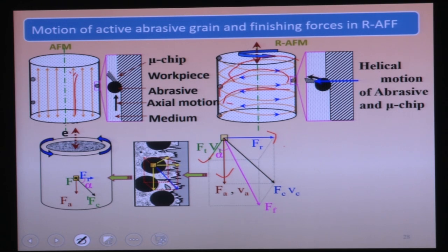Okay, so as it is flowing through a spiral path, it will generate a cross-hatch pattern on the workpiece surface. So these cross-hatch patterns are generated on the workpiece surface. This is actually helpful to retain the oil during the actual polishing of the cylinders of the engine, the engine cylinder, and also it is traversing more path. So that's why more area is covered. It is not covered because these abrasive particles are moving in a straight line path. So it does not cover more area, but in this case, in the RAFM process, it is covering more path.